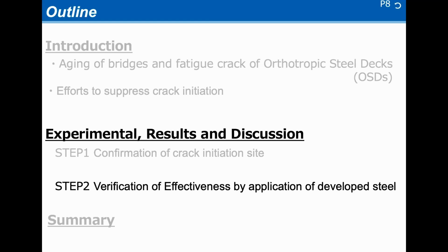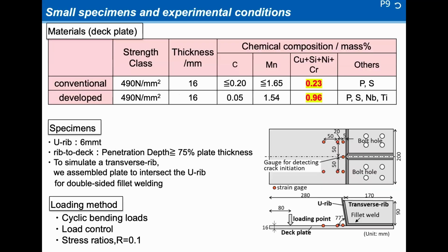Secondly, verification of effectiveness by application of the developed steel. A schematic representation of the test specimen is shown at the bottom. It's composed of U-rib and deck plate. In addition, to simulate a transverse rib, we assembled a plate to intersect the rib for double-sided fillet welding. And strain gauges were placed at the locations shown to measure strain during the test.